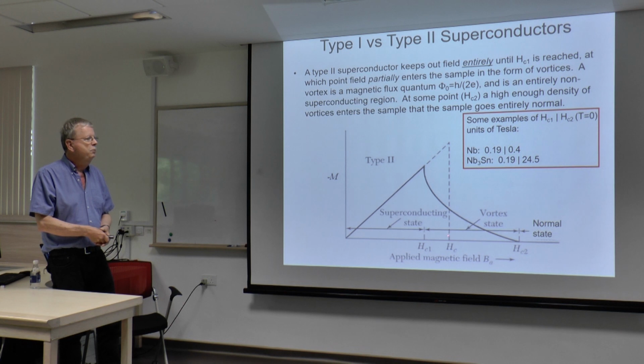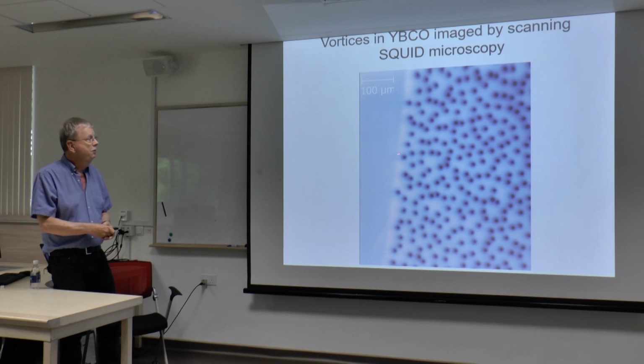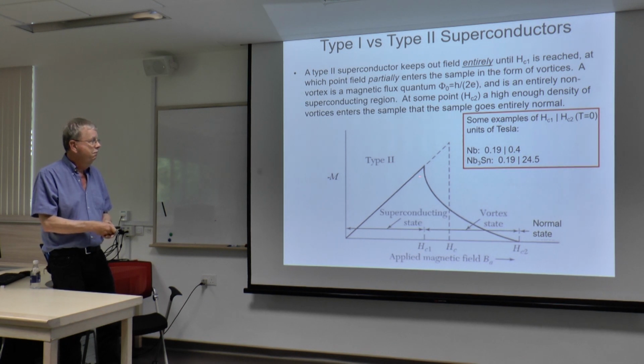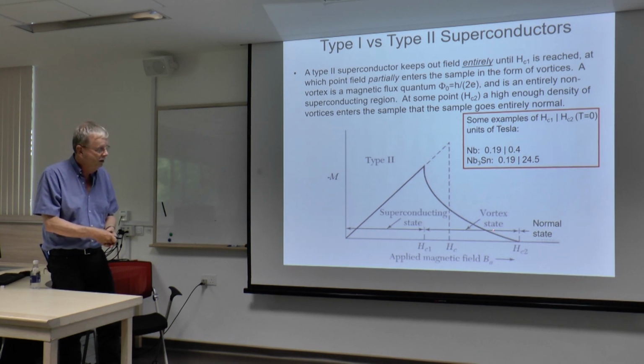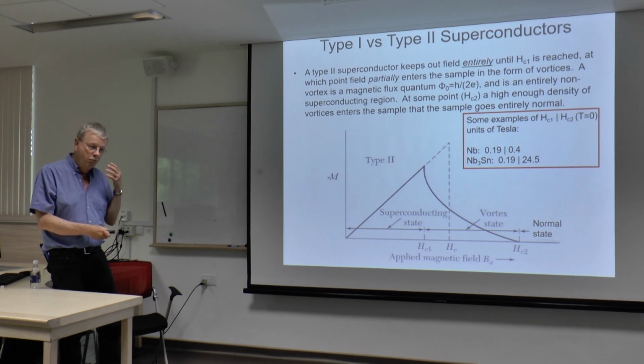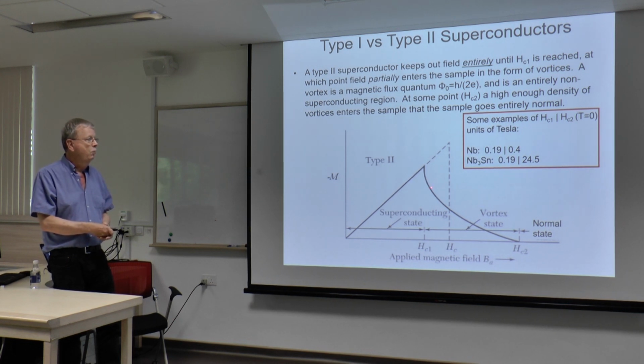Now you get resistivity that's zero by having connected pathways that don't have to go through a flux line, and so you can have some amount of diamagnetic susceptibility, as you see. It's not perfectly diamagnetic, but you still have some diamagnetic susceptibility. You have rho equals 0, but no problem with zero resistivity, and you have practically a wire for making superconducting magnets. So type 2 superconductors are what are used industrially, and this is a very important distinction.